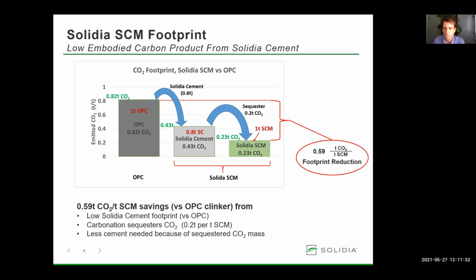The waterfall chart illustrates footprint reduction starting with our baseline 1 ton of OPC clinker, which emits 0.82 tons of CO2 at the kiln. As explained on the previous slide, less than a ton of Solidia cement is needed to make a ton of Solidia SCM. In this case, we need 0.8 tons of Solidia cement, which has a footprint a little more than half of OPC's footprint. A further reduction in footprint comes from sequestering 0.2 tons of flue gas CO2, bringing the final footprint of 0.43 down to 0.23 tons CO2 per ton of SCM, a total reduction of 0.59 metric tons of CO2. I should mention that we do not include parasitic process losses here, which are small relative to the overall savings.